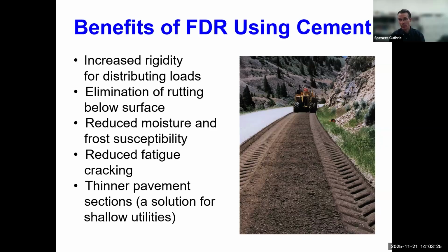When we use cement, even in small concentrations, for example, 2% to 6% by weight of dry aggregate is really common. We get all of these benefits: increased rigidity for distributing loads, an almost entire elimination of rutting below the surface, reduced moisture and frost susceptibility, reduced fatigue cracking of the asphalt layer, and we can use a thinner pavement section, which is frequently a solution when we have existing utilities that were constructed in a shallow manner.